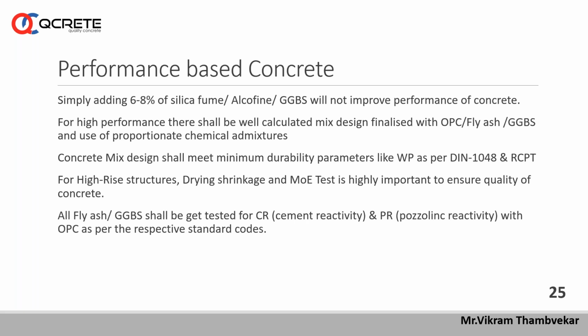And of course that durability doesn't show immediately because of the reactivity of the supplementary material with the cement. It starts after some period, after 28 days, 30 days, 45 days or something. And all these durability parameters should be checked up to 2 months, 3 months, etc., to ensure what is the effect on hardened concrete. So these are the tips for performance based concrete.